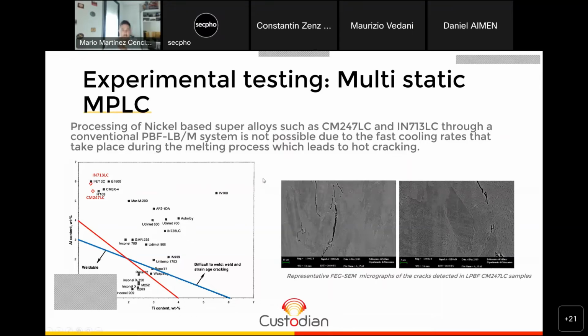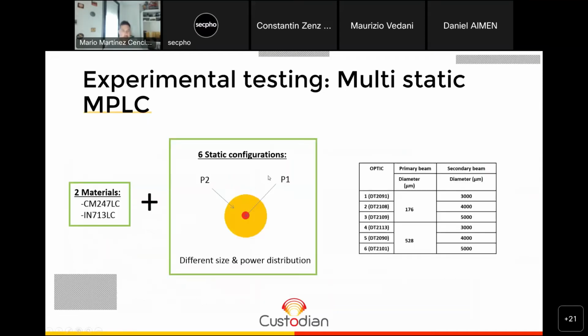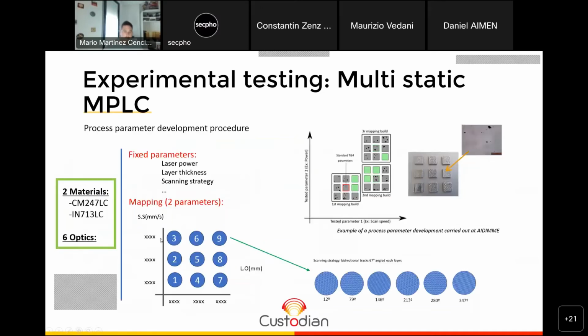And so the idea of Custodian was to tailor the beam shape to perform this preheating and postheating during the process, right? As I said, and as shown before, we have two materials and we have 6 static configurations. We have six optics, which combine different primary and secondary beams. And for each of the optics, we did a design of experiments to find out ideal conditions, let's say, where these materials can be processed, right? So from now on, we will see some samples, and I just wanted to remark that this is a common strategy for all the tests that we did.